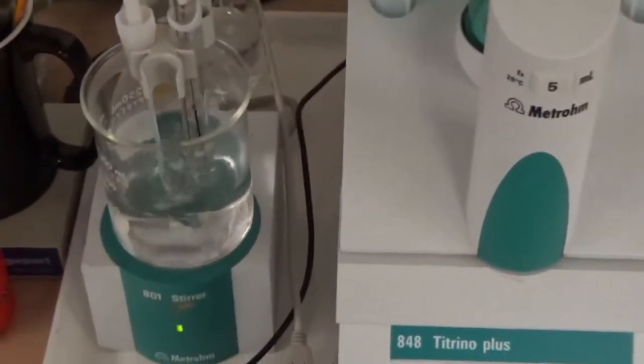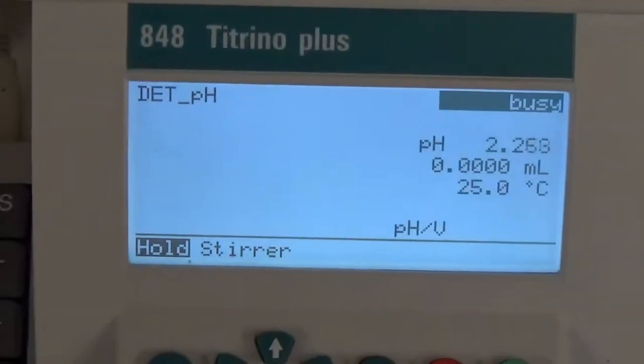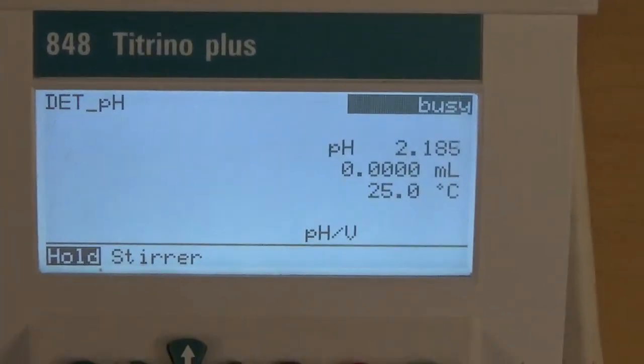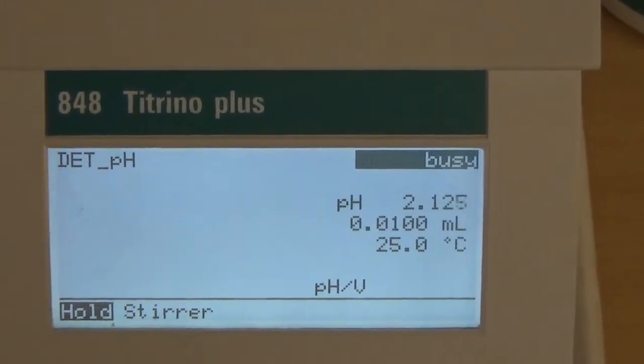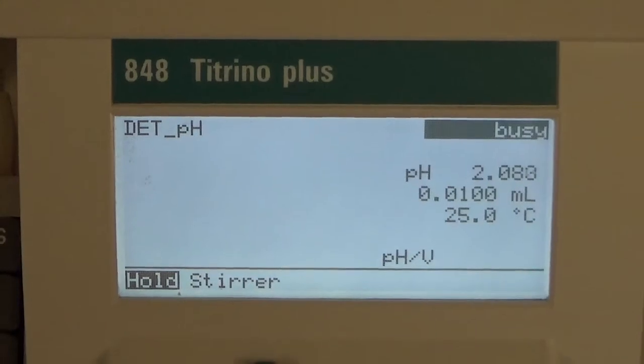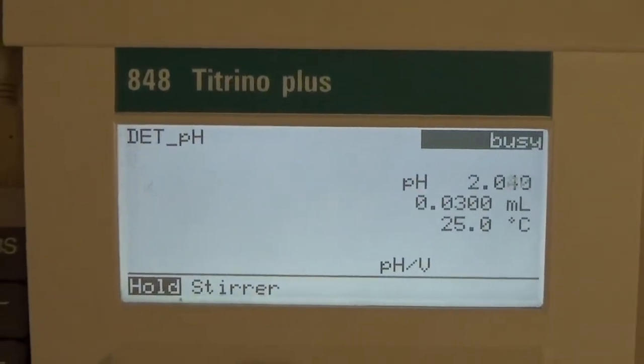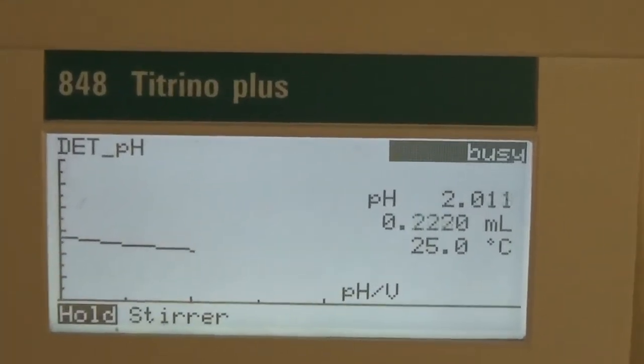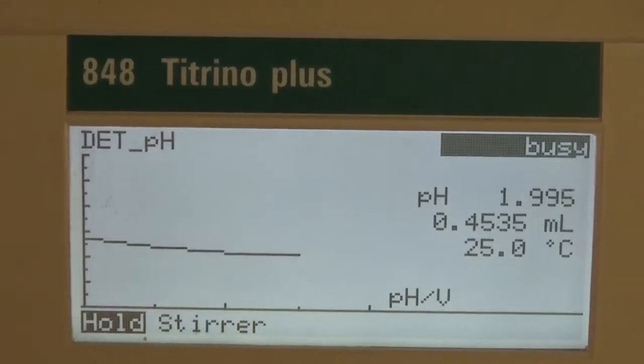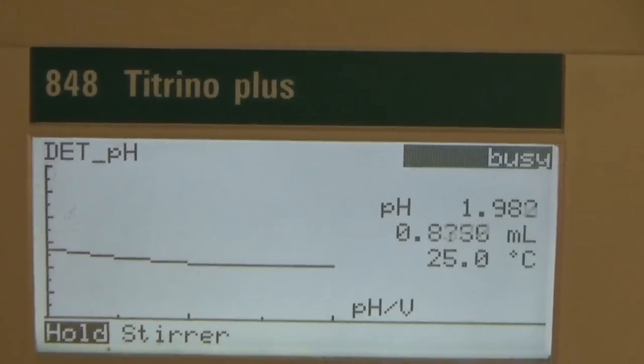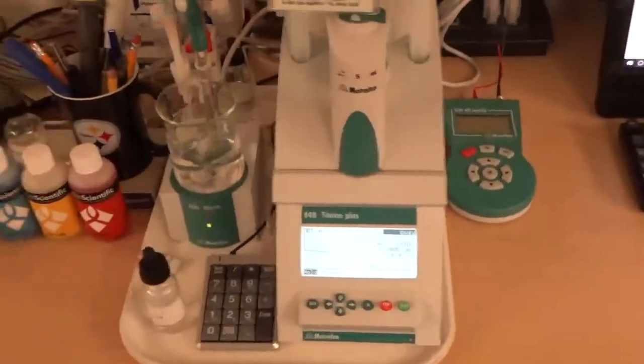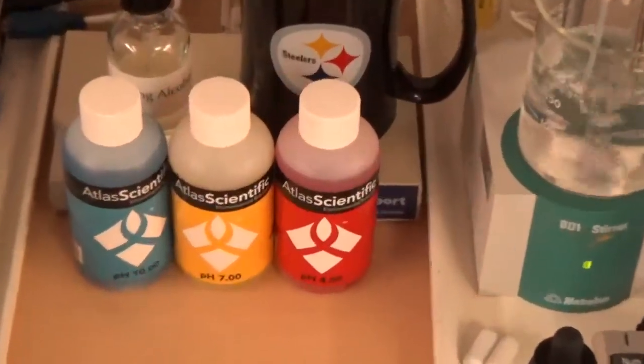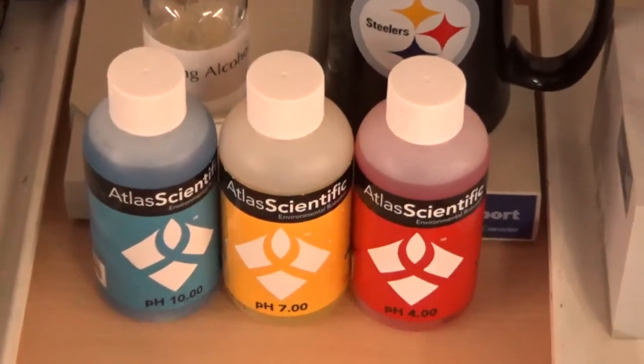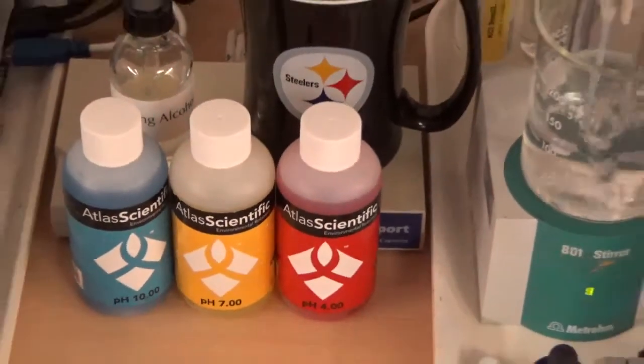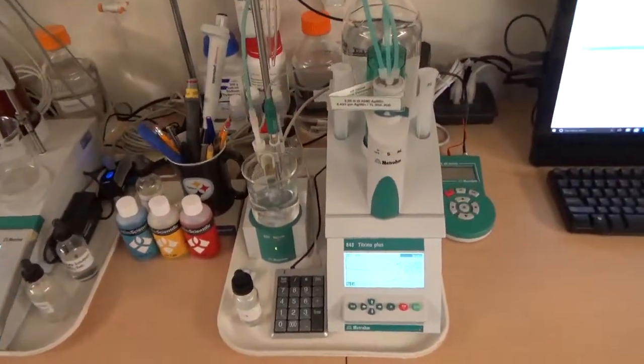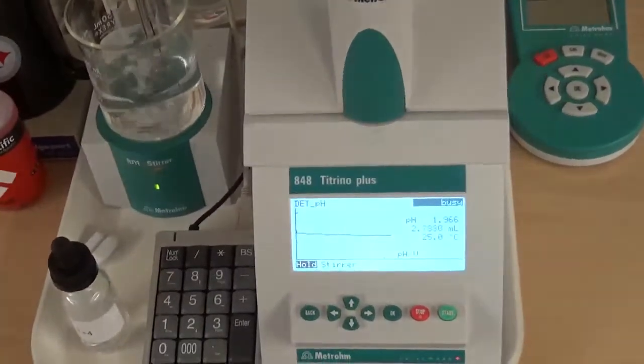As soon as the titration starts, the stirrer starts and the small screen starts showing the titration plot. Every time we do acid-base titration or alkalinity or pH test, we first calibrate the pH meter or the pH electrode with three different buffers of pH 4, 7 and 10. The pH electrode has to be calibrated every time before you start the titration or pH determination.